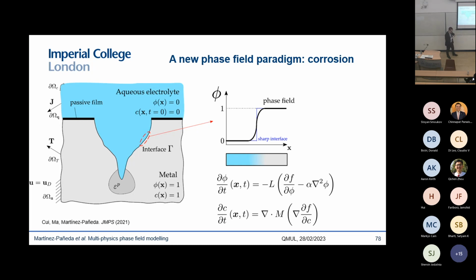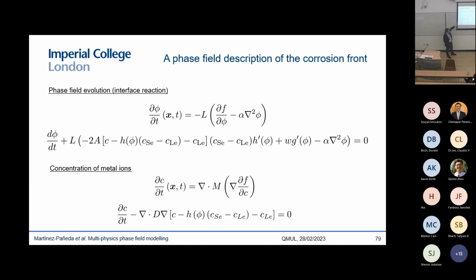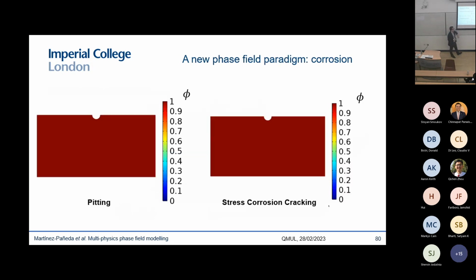So it's describing how the metal is dissolving as part of the corrosion process. And I'm not going to get into the details of the phase field equation. It's more based on phase field solidification models, like the KKS model, and not that much on the fracture ones. But at the end of the day, in the simplest form, you end up with two equations. One for short-range interactions, so material dissolution, the phase field describing how you're losing material, and then one for the long-range interaction, which is basically the diffusion of metal ions far away from the interface.